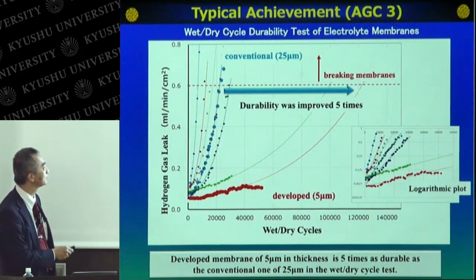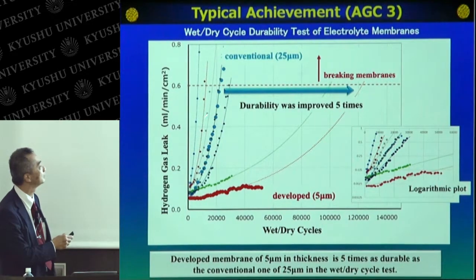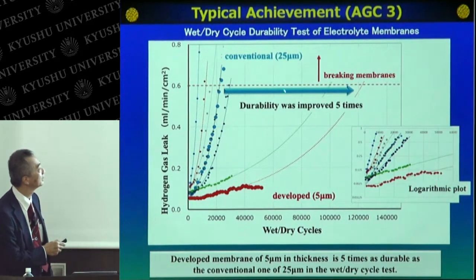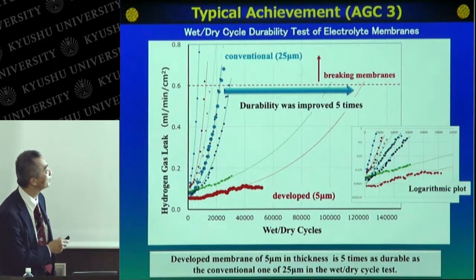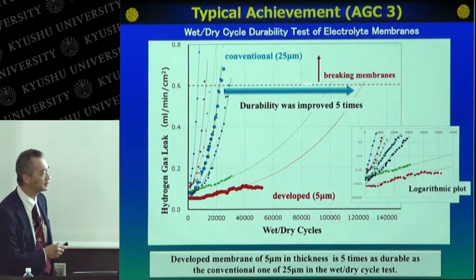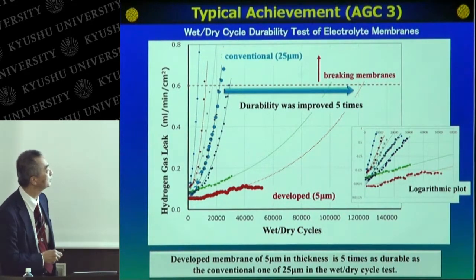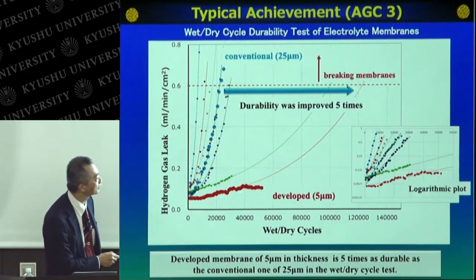The vertical axis shows hydrogen gas leak. When the leak level exceeds this breaking point, the membrane is regarded as broken. This blue line shows the results of the conventional membrane with a thickness of 25 micrometers. The 25 micrometer membrane is broken at about 20,000 wet-dry cycles. But you can see this red line.